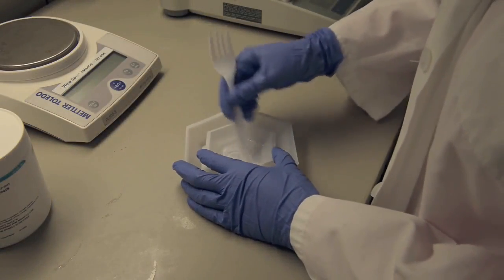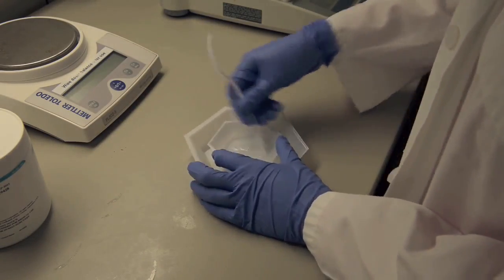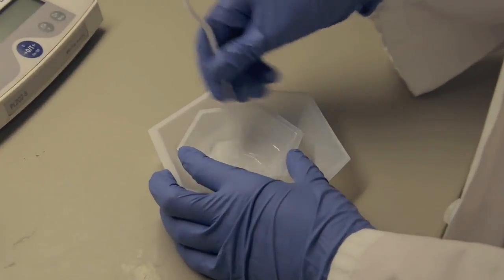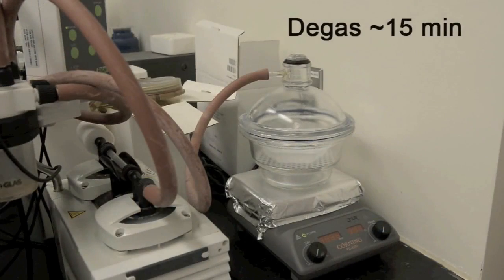Thoroughly stir the mixture until it is filled with bubbles, then place the mixture into a vacuum chamber and degas under vacuum for 15 minutes or until all bubbles have disappeared.